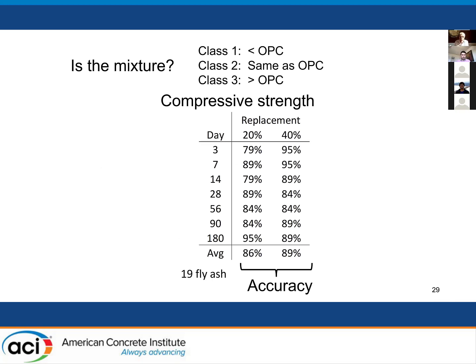So here's the question. Is the mixture less than OPC, the same as OPC, greater than OPC? And we're going to look at compressive strength. This is a 20% replacement. This is a 40% replacement. These are different days. And you can see here at 7 days, it was 89% accurate for 20% replacement, and it was 95% accurate for a 40% replacement level.